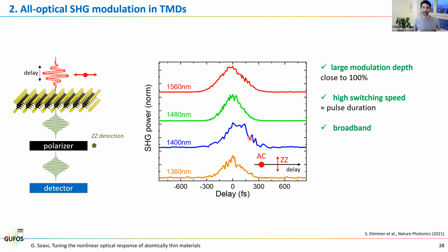So that's why my feeling is that the best would be to take really MoTe2, because then you can pump at 1 micron, you are above gap, and your second harmonic will be at 500 nanometers. So Alison, if you want to make a sample for us, I'm very happy.